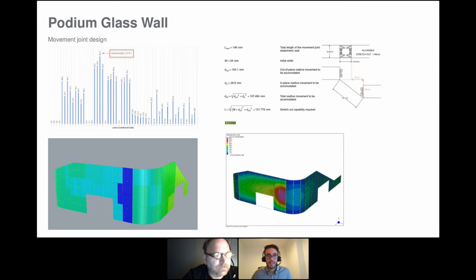For the design of the movement joint, what we had to do was go through all the load cases we analyzed and pick up the ones generating the worst-case relative movement between flat and curved, or curved and curved, glass panels. As you can see on the top left, this diagram shows a specific point, in this case the interface between the flat and the curved panel, with all the relative deflection captured for each load case analyzed for the wind. From this, we picked up the worst-case scenario. And basically what we did was design the width of the movement joints to be able to absorb the stretch generated by the radial and tangential differential movement.